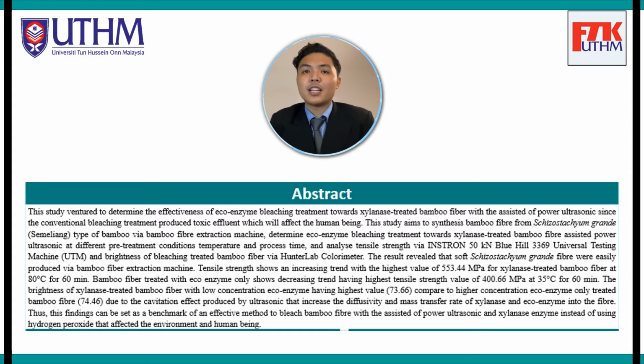The brightness of XYLANASE-treated bamboo fiber with low concentration ECO-ENZYME has the highest value of 73.66 compared to higher concentration ECO-ENZYME-treated bamboo fiber, which is 74.46, suspected due to the cavitation effect produced by ultrasonic that increases the diffusivity and mass transfer rate of XYLANASE and ECO-ENZYME into the fiber. This finding can be set as a benchmark of an effective method to bleach bamboo fiber assisted by power ultrasonic and XYLANASE enzyme instead of using hydrogen peroxide that affects the environment and human beings.